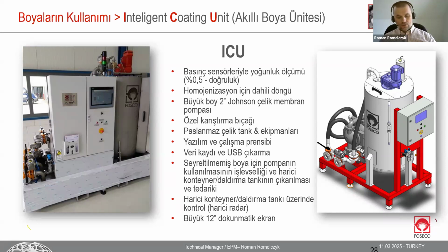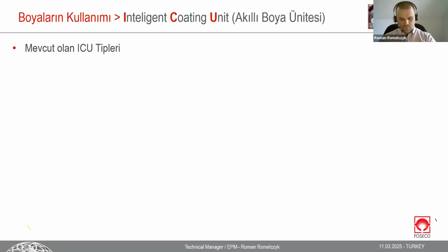The unit will dose the coating as delivered, in a calculated amount, with alcohol or thinner, we can say water or alcohol, mixed together in a preparation tank. The density and viscosity which you want to have, you put on the LCD screen in the touch panel, and the unit itself will take care to give you exactly the coating which you expect. So if you put 1.25 gram per cubic centimeter, the unit will prepare for you exactly this value.